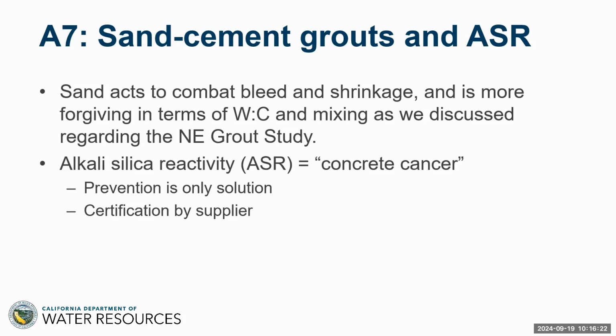So the effect on our grouts would be that if we don't use the right aggregate, i.e. if we use the wrong reactive aggregate, then we run the danger of our grouts cracking and expanding and therefore increasing in permeability with time. It cannot be stopped. Now, in my opinion, once it starts, you can't stop it. So what do you do? You try and have strong prevention.